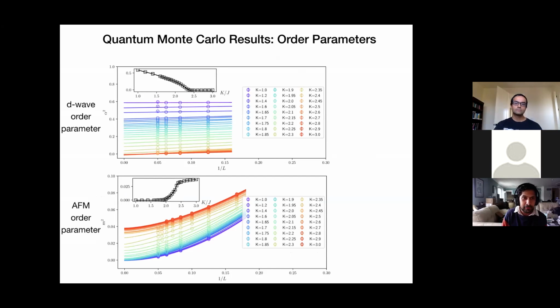Yeah. So then you can study. Now you can do 1/L scaling, and it's very obvious that the D wave order parameter is non-zero in some regime. So this is different values of K, and this is the D wave order parameter versus 1/L. So clearly there's a regime in which it is non-zero. And similarly, you can do scaling of the antiferromagnetic order parameter, which is also non-zero in some regime. The main message, don't worry about the numbers, is that you can show it is non-zero and there is no ambiguity.